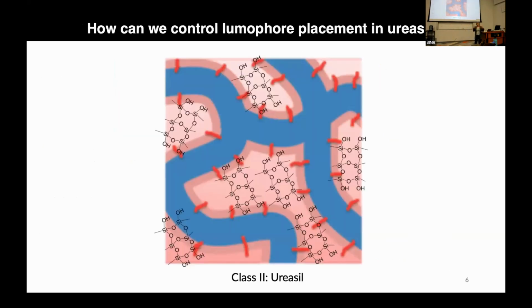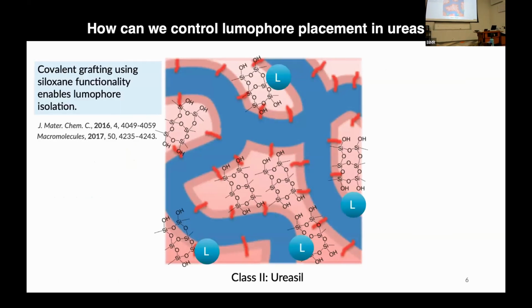So in order to make our ureasil luminescent, I'm going to put a caveat there. I'm going to give a spoiler. Actually, ureasils themselves are a bit luminescent, and we'll see that in a few slides' time. But to add the main luminescent species, we can add the lumophore in a few ways. So first of all, for example, we can covalently graft our lumophore. If we modify our lumophore, add on the same tetraethyl orthosilicate groups, for example, to parts of the lumophore, we can selectively graft our lumophore so it sits within the silica domains of our ureasil.